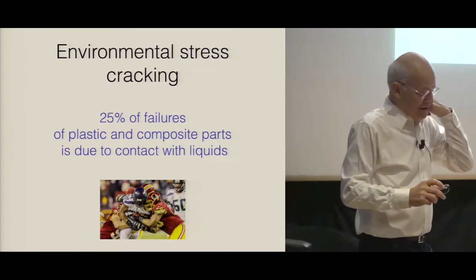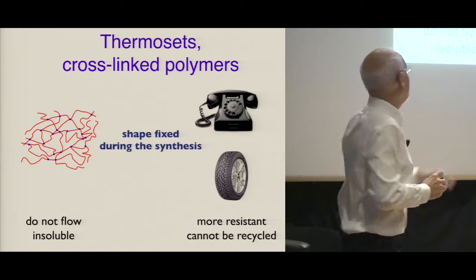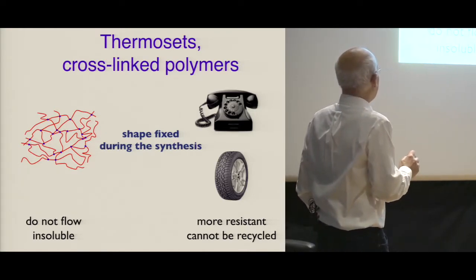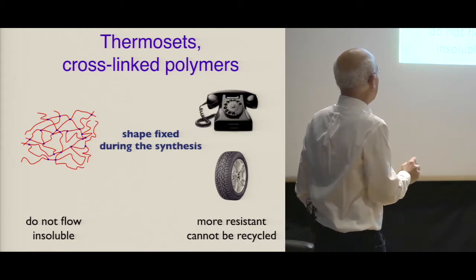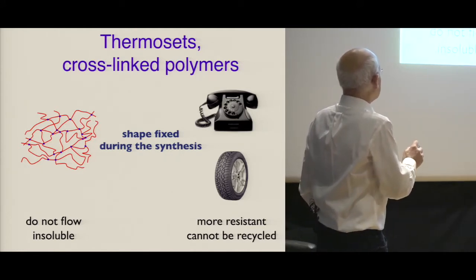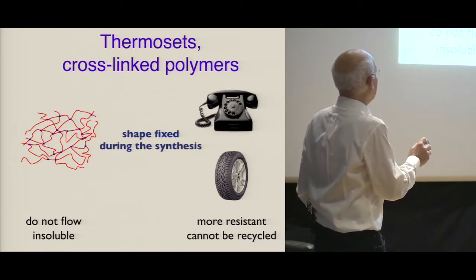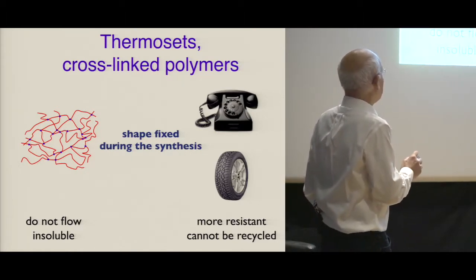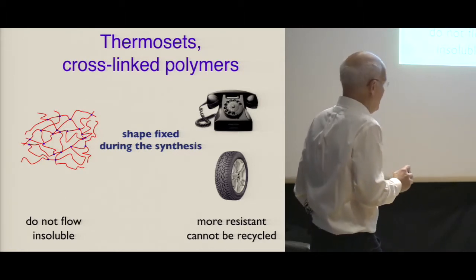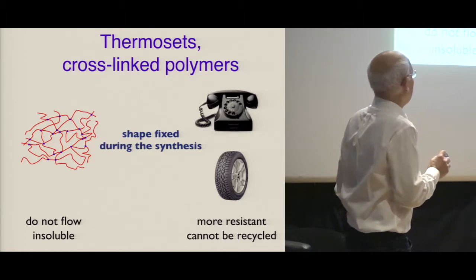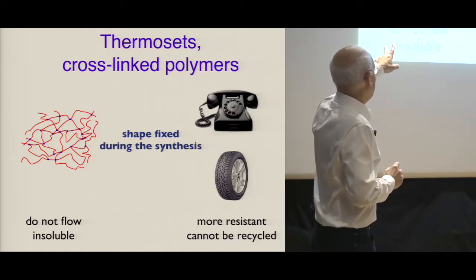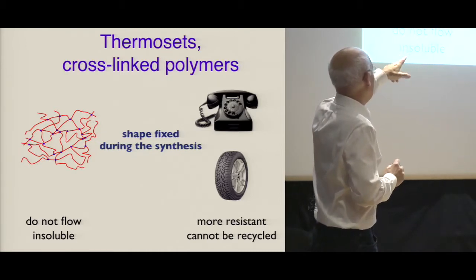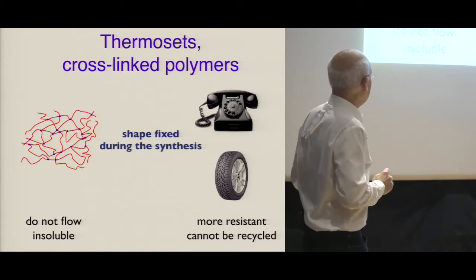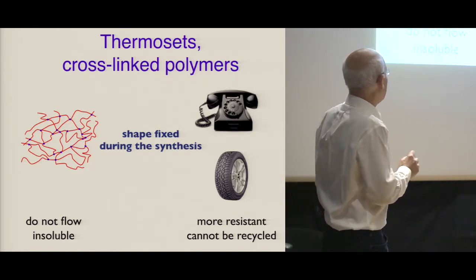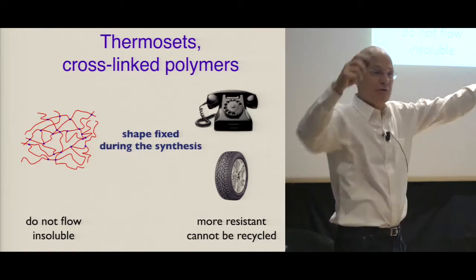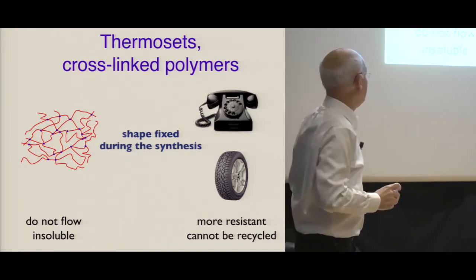What we know is that if we cross-link a polymer, so instead of having long chains, we make a network which is cross-linked, then these cross-linked polymers, which are called thermosets, are very resistant to stress cracking. And actually, these were the first polymers. There were two categories of polymers. There are polymers which are cross-linked, which do not flow, cannot be processed once synthesized. And of course, they are insoluble because it's a network. So you can swell the network, but you cannot separate the molecules because they are covalently linked.